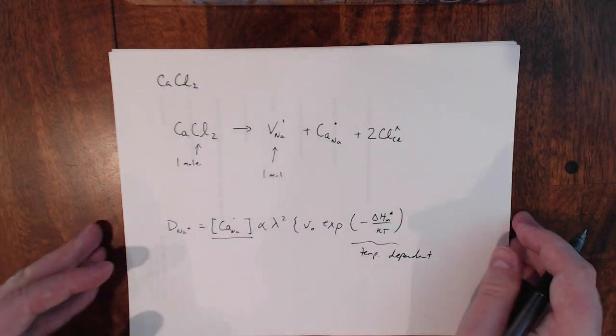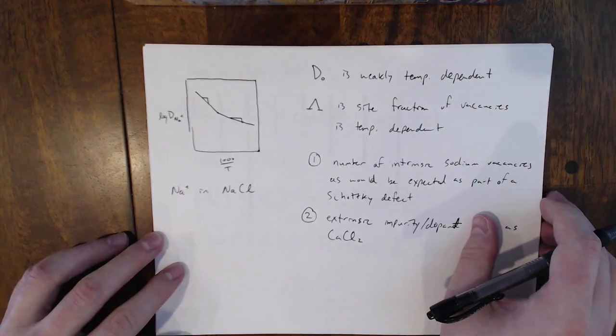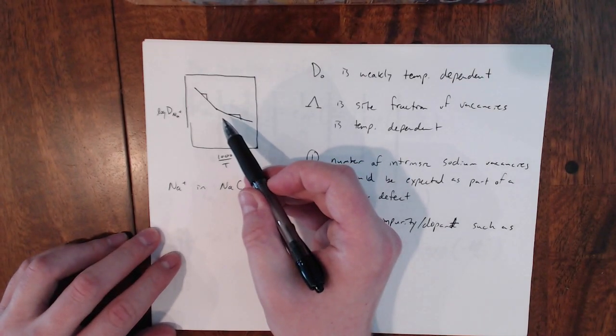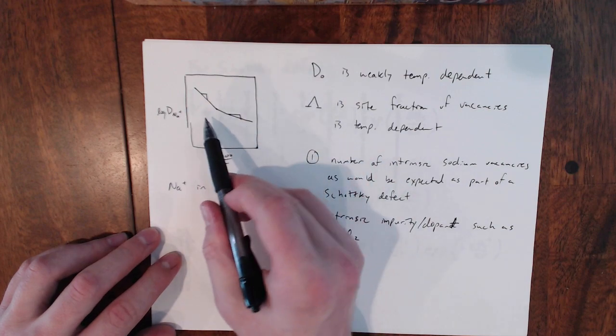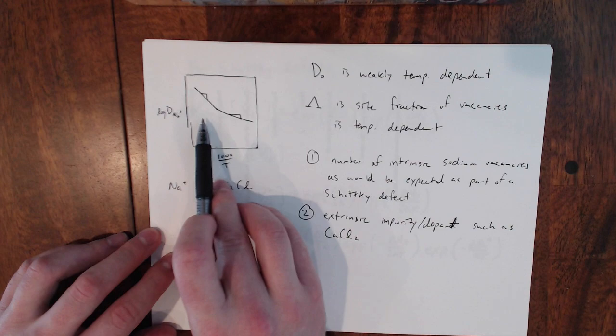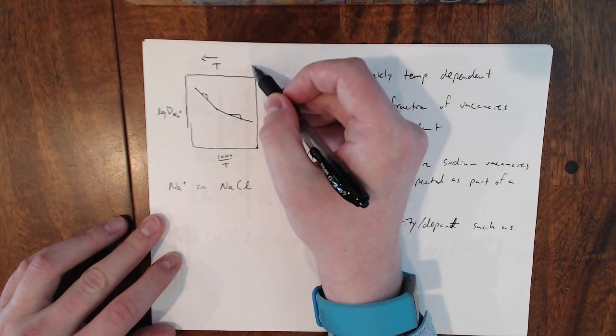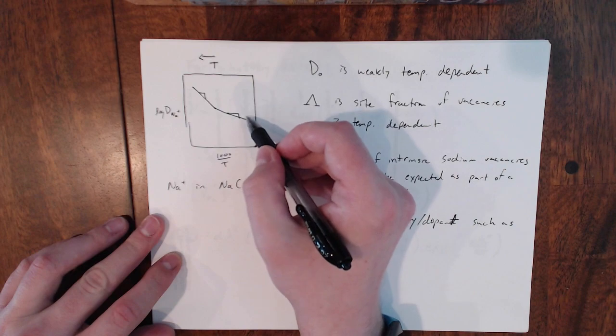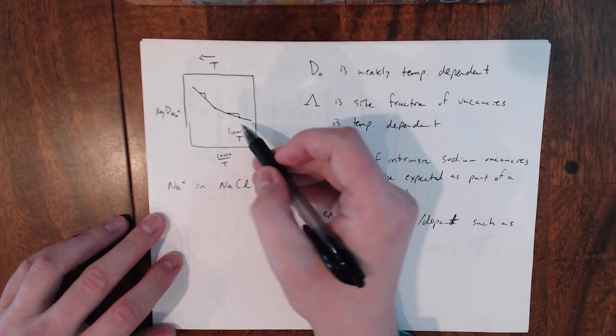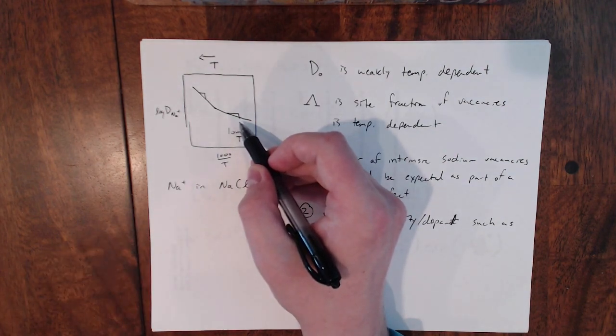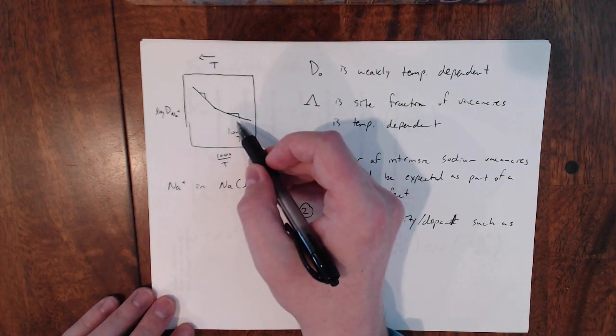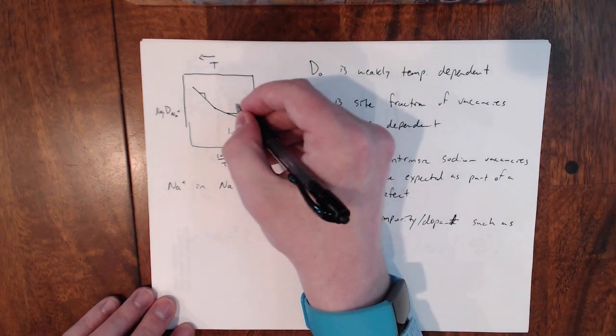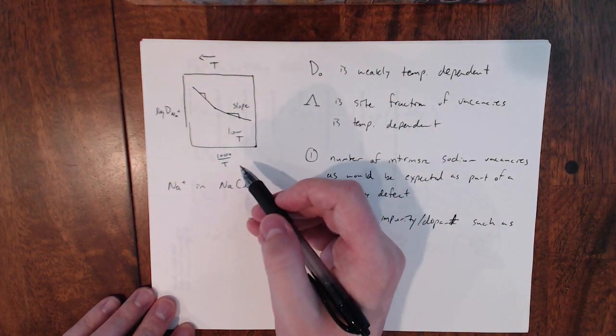And so now if we think back, and I'm going to go back to this curve that we had before, right? This tells us basically what's happening then is that we have two regions of this curve. One of them, and so if we think about the way this is going, is temperature is increasing from the right to the left. So this is the lower temperature region here, low T. So here we see a slope, and this slope is going to be governed by that extrinsic doping, right? And so we have the slope here is related to that expression we just developed.